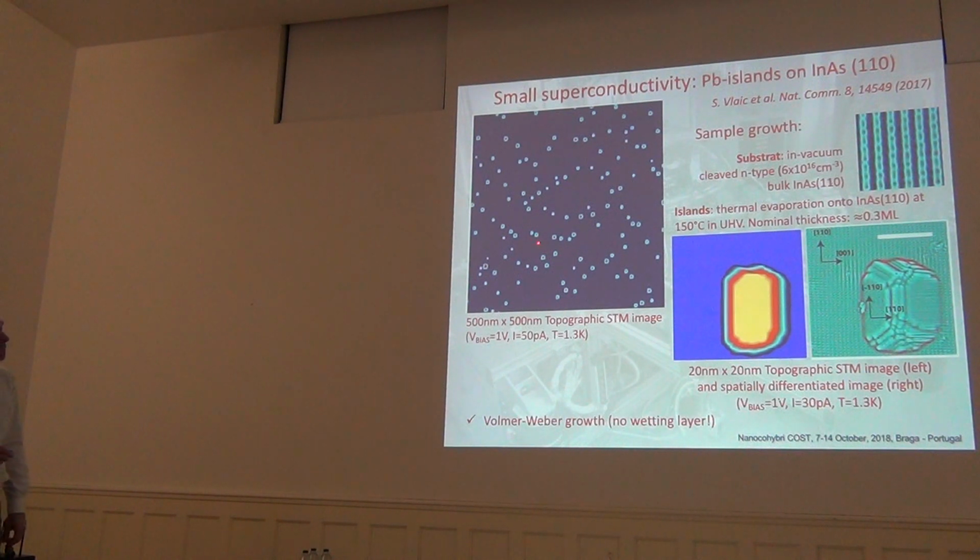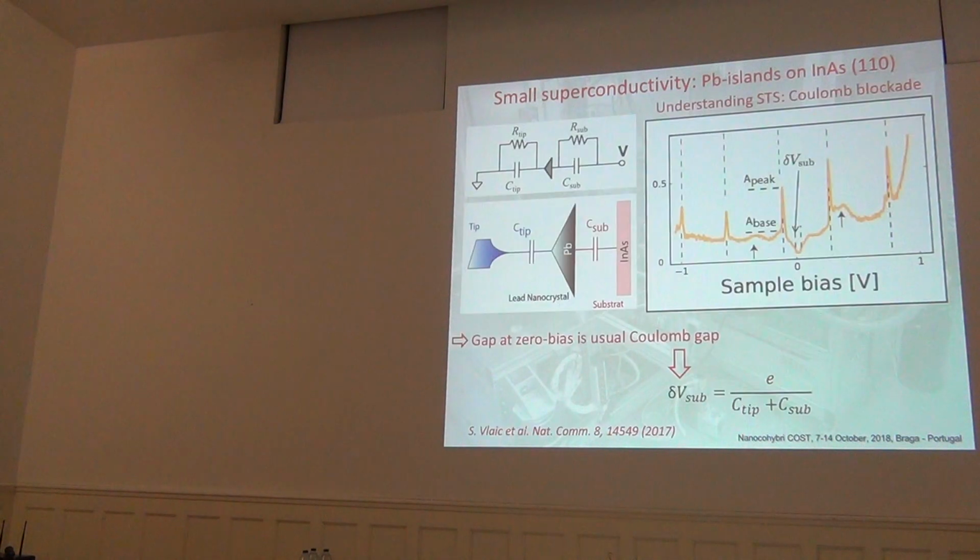there is almost no electric coupling between those islands and this two-dimensional gas, for two reasons. One is that below the lead, this two-dimensional gas depletes, so it gets away. Another reason is a very strong mismatch of K Fermi, of wave vectors, between a semiconductor and a metal. So simply, our electrons from lead cannot go in because there are no places at this K value. So finally, with our islands sitting on indium arsenide, the most important coupling is just capacitive coupling. That's what we found.